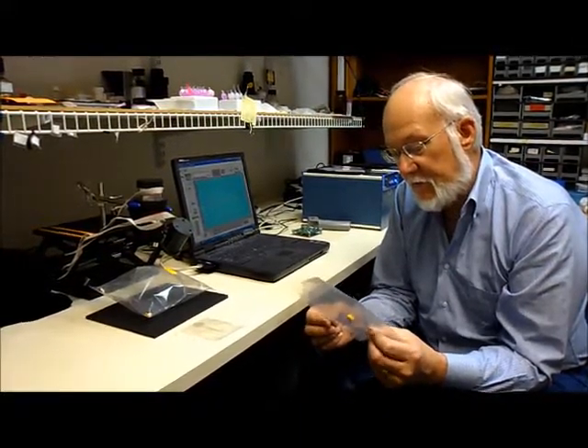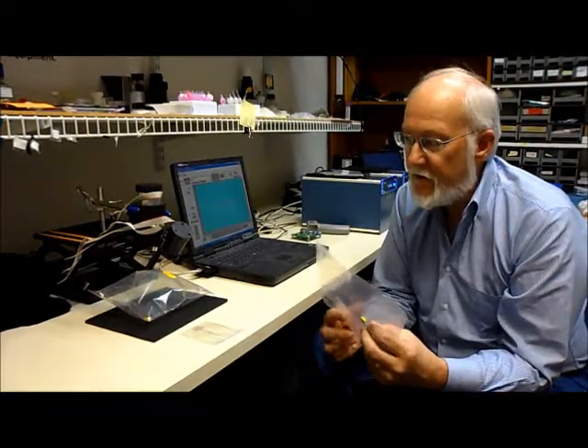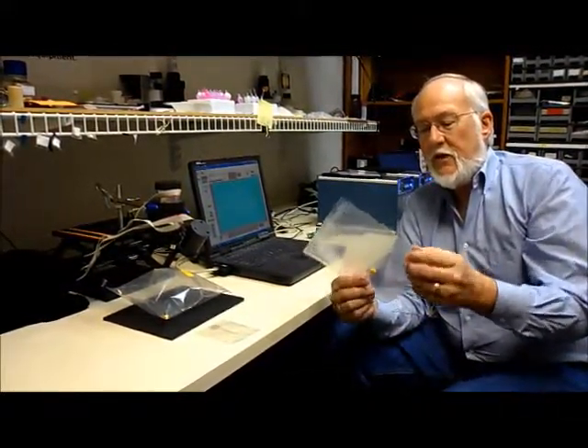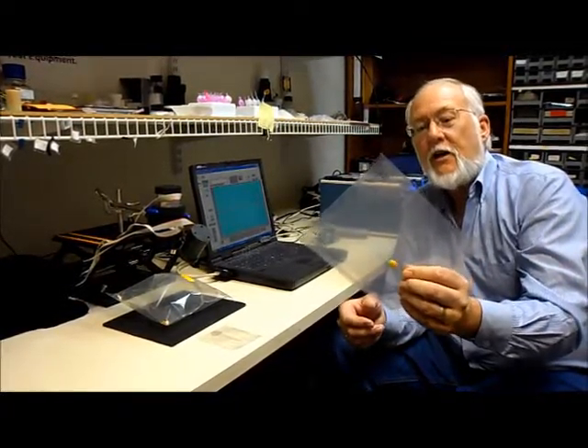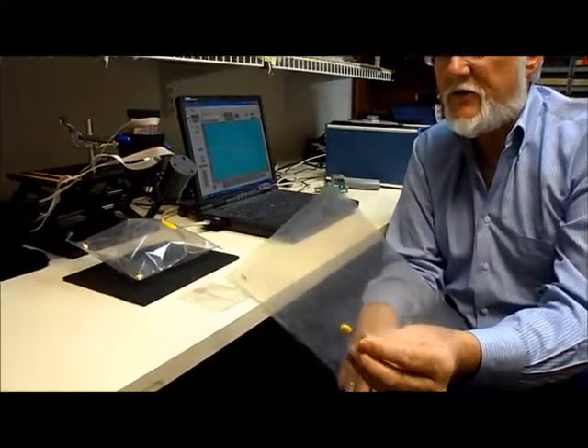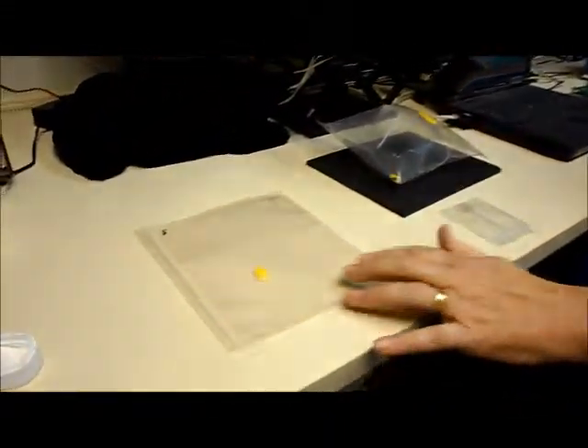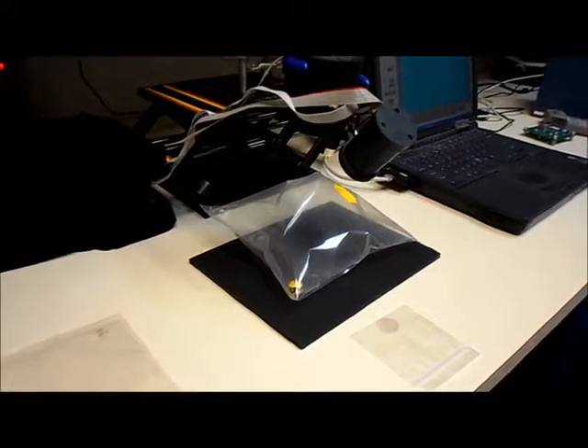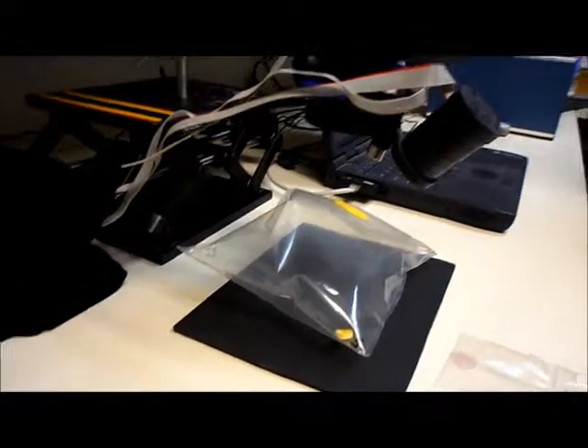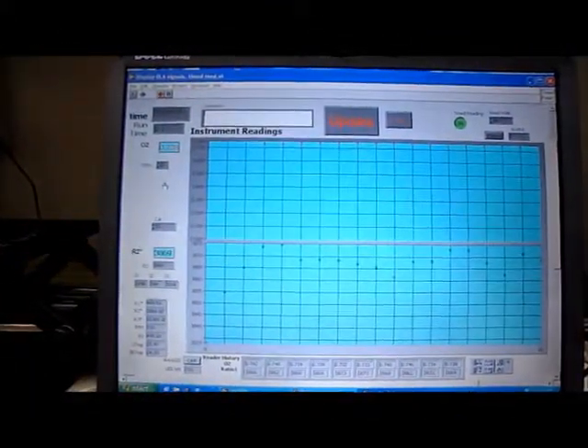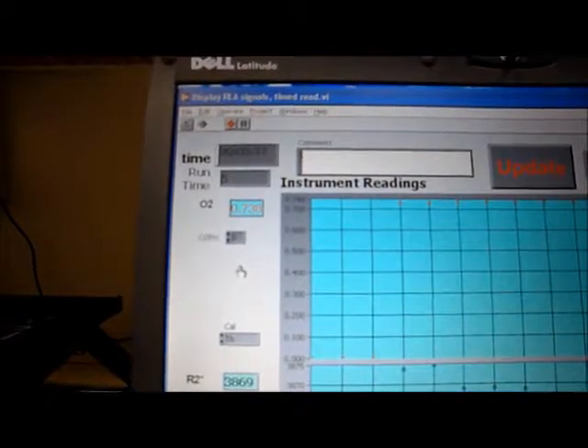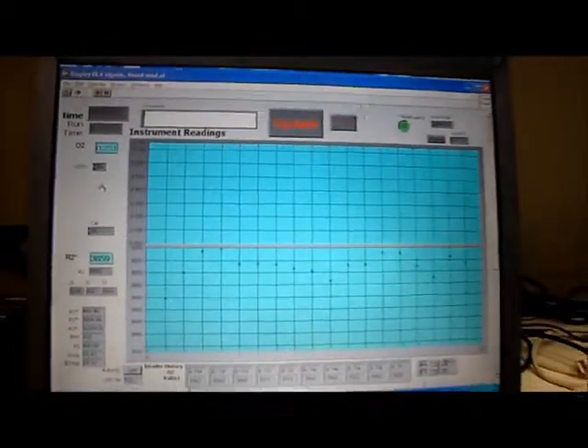Having given you some visual demonstrations of the responsivity of films and different configurations that we've created, I want to now show you indeed how the films can perform as we analyze with our instrumentation here with the optical reading. I've got a particular film here where you can't even see the oxygen sensing dye that's contained within this polymer. It's a multi-layer laminate, but I have a sample here of that created into a pouch that's sealed and has been filled with nitrogen gas, and we're doing a measurement of it right now. Over here on my computer screen you can see that we're tracking the oxygen on a 10-second interval, doing updates here of the measurements. I'll explain in a minute, but indeed we've got like a 0.7% oxygen in the environment as measured with the system.